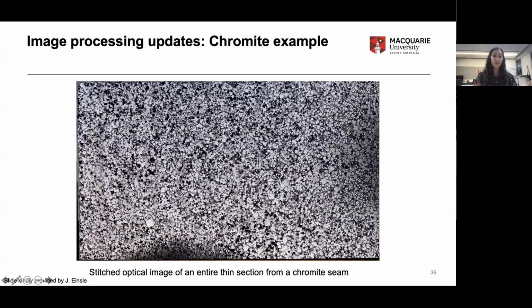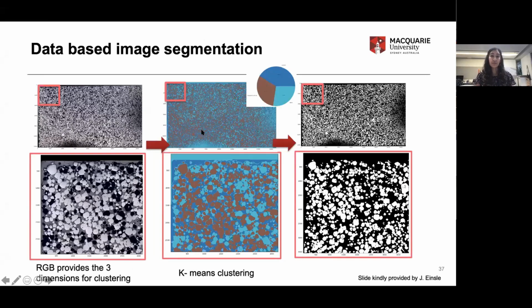So this example is actually of a red, green, blue image. So this is just an optical image of a chromite thin section, and it's been stitched together. What we've done here is exactly the same way in which we were exploiting the grayscale intensities from the SEM micrographs. The red, green, blue color channels actually provide 3 dimensions for us to try and identify clusters in this case. And this time we're using machine learning to train our code so that it can get a better understanding of what those 3 different clusters might be.